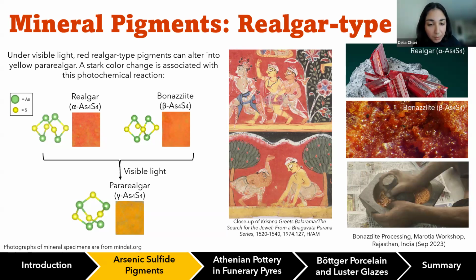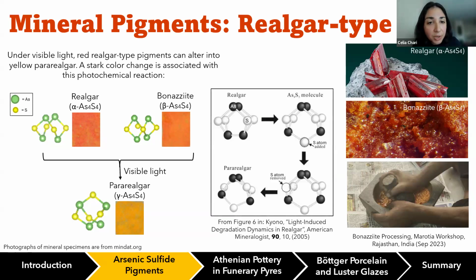From a more mechanistic perspective, the way that this reaction occurs is that with light, there's initially a slight oxidation of the arsenic sulfide structure, which releases a free sulfur atom that attaches itself onto the arsenic sulfide molecule, creating this energetically unstable structure that eventually transforms again into this different structure known as para-realgar. So para-realgar has the same stoichiometry as bonazziite and realgar. It's just a rearrangement of these arsenic and sulfur atoms that leads to a completely different phase with a different color.